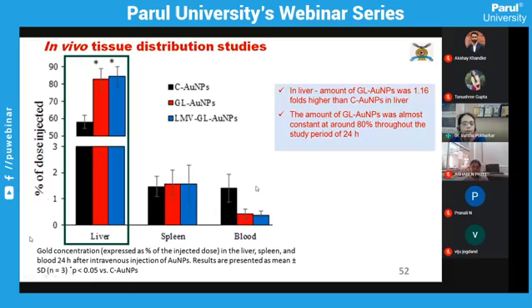The quantification again was done for the in vivo tissue distribution studies, and you can see here that the amounts in the liver are considerably high as compared to the spleen and the blood. The amount of glycyrrhizin reduced gold nanoparticles was almost 1.16 fold higher than the citrate reduced gold nanoparticles. But what is more important is that the amount was constant at around 80% throughout the study period of 24 hours. It did not decline.